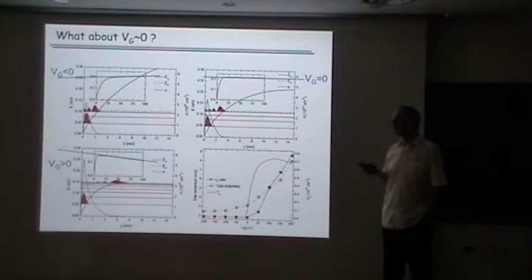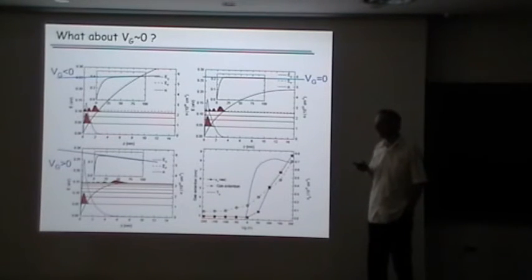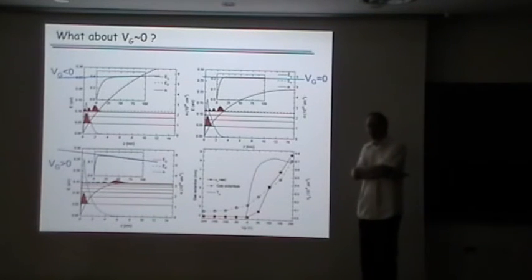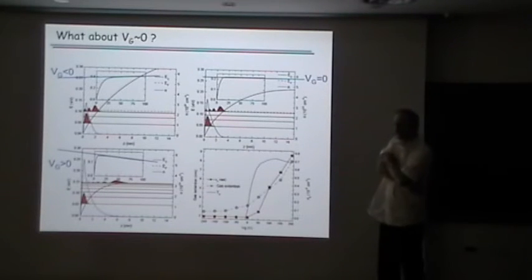Yeah, that's right. And also, if there is something new, this is for very, very low thicknesses of lanthanum titanate, and even in their view, low means below 5 unit cells. And in our case, below 5 unit cells, like for everyone, there is no conductivity at all. So it could be just a material problem, and maybe in a few years, it will change. Yesterday I tried to explain to you that maybe it's more deep, that for some electrostatic or strain reasons, you cannot get charges in the system for smaller thicknesses. But you're right, there is no sign of exotic physics up to now.